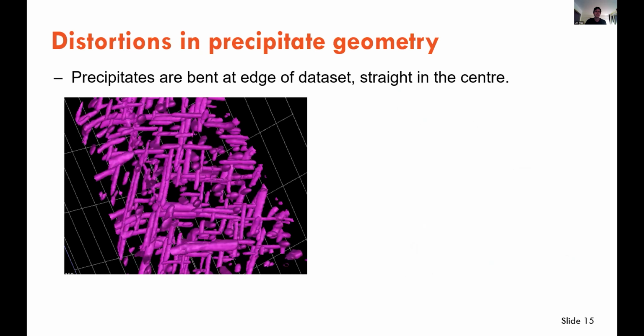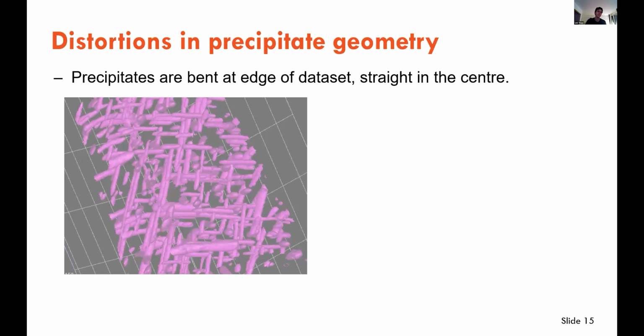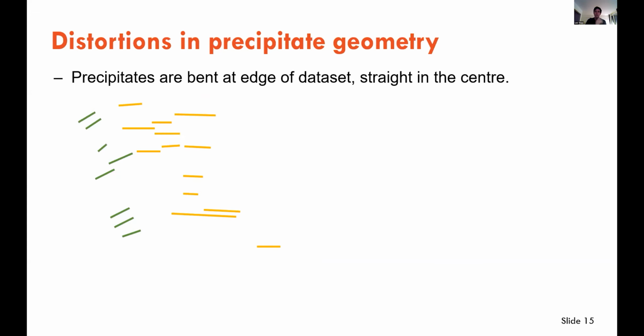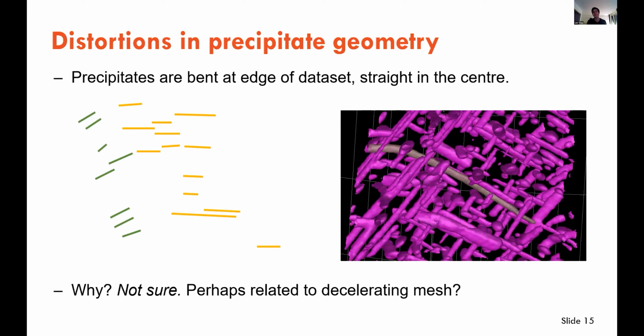Still in the precipitates, there are some distortions at the edge of the data set and straight in the center. So a very quick analysis is just to look at all the precipitates in the file, draw lines over those in the core and the edge, and show that they're not exactly parallel. This particular precipitate is straight in the middle and bent at the edges, which is not what we expect from TEM studies of the material. The precipitates should be straight and not bent everywhere.